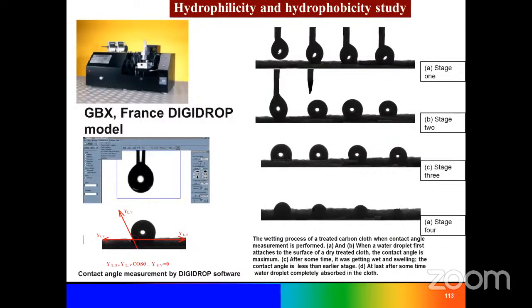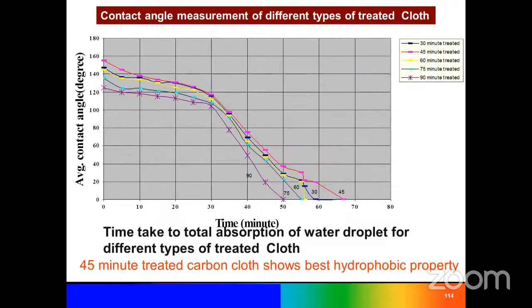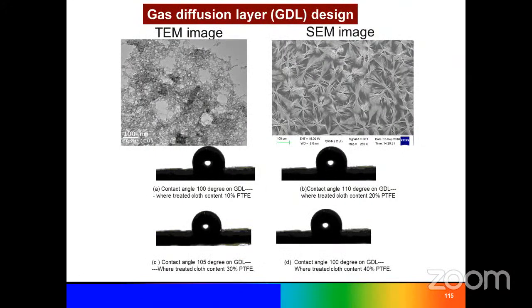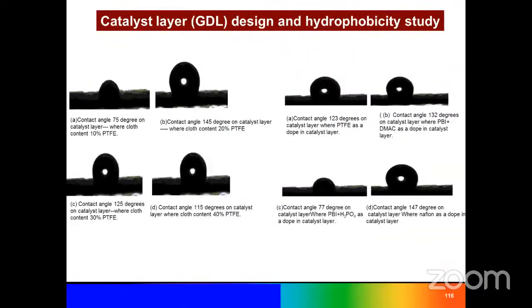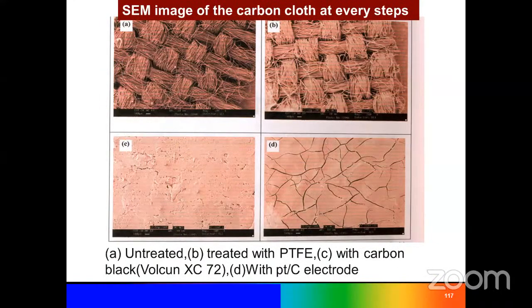Where the contact angle is higher, that means it is giving higher hydrophobic properties. Then finally we check the average contact angle, to see which doping material is giving the high average contact angle. Then we checked the surface morphology. Then finally we optimized the higher percentage of PTFE and the platinum materials. This is the surface morphology of the carbon cloth coated with this platinum doped carbon material.